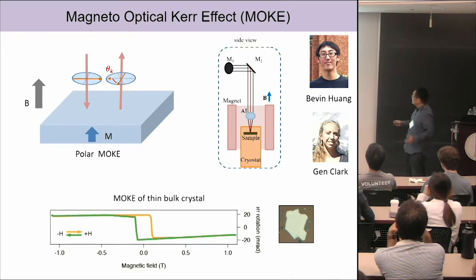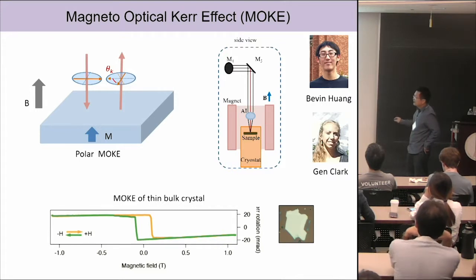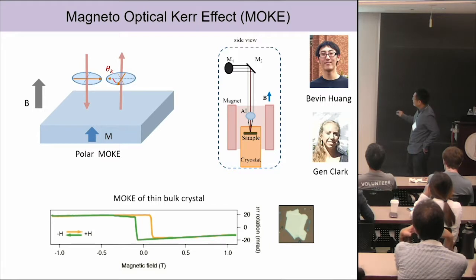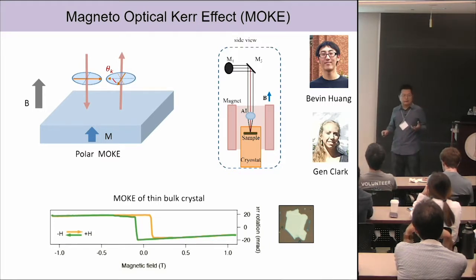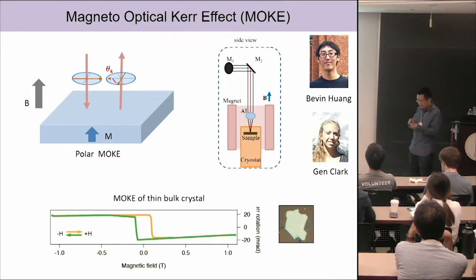So the real measurement you should do is to measure the Kerr rotation as a function of magnetic field, as I show here. There are 2 curves here, right? One is the magnetic field scan up, the other is the magnetic field scan down. If you measure the Kerr rotation as a function of magnetic field, it's called MOKE. If you see a hysteresis, that tells you you do have ferromagnetism in the system. Okay, that's important. So from now on, if you see a hysteresis, you know there's ferromagnetism. That's the main technique we're going to use. The measurement down here is in a bulk crystal.